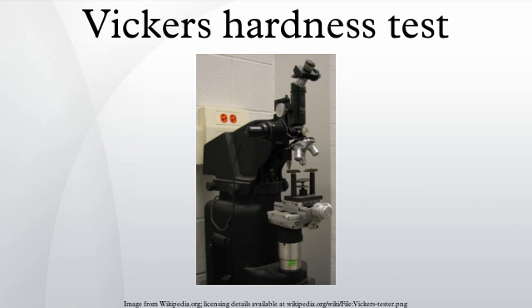Application: the fin attachment pins and sleeves in the Convair 580 airliner were specified by the aircraft manufacturer to be hardened to a Vickers hardness specification of 390 HV5, the 5 meaning 5 kilopond. However, on the aircraft flying as part of Flight 394, the pins were later found to have been replaced with substandard parts, leading to rapid wear and finally loss of the aircraft. On examination, accident investigators found that the substandard pins had a hardness value of only some 200-230 HV5.